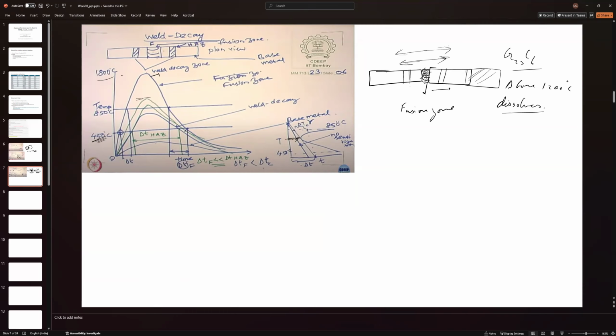Or again, when we reach 850 degrees Celsius, when we are in between this range, 850 degrees Celsius and 450, we have the maximum amount of precipitation of chromium carbide. So we are forming chromium carbide, and that's the region where the temperature reaches this maximum region, where you will see maximum IGC attack. Okay, so this is what happens in weld decay. So now you know.